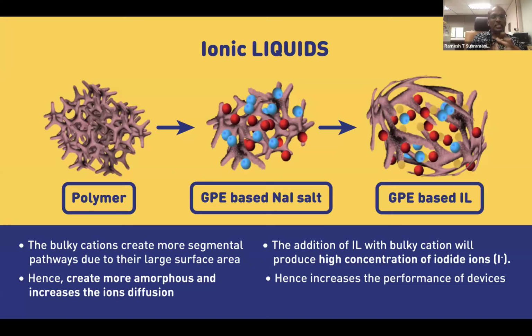Ionic liquid is another material that we can use to increase the conductivity, where we can replace the conventional organic solvent. So they will create more amorphous structure and increase the ionic diffusion. And the addition of ionic liquid with a bulky cation will produce a high concentration of iodide ions in this case, because we are using sodium iodide as a salt.